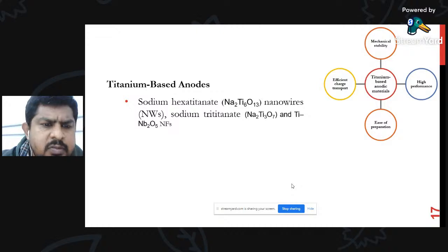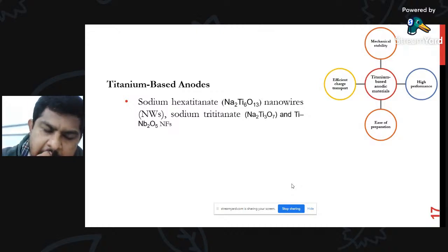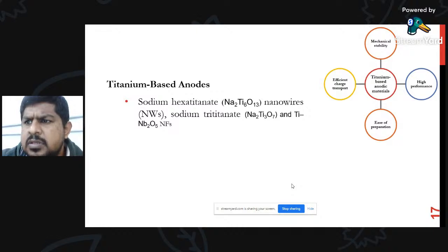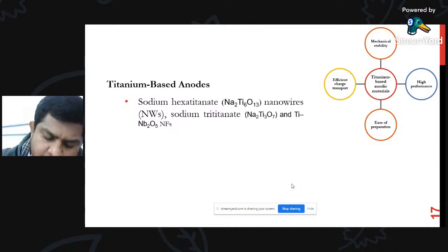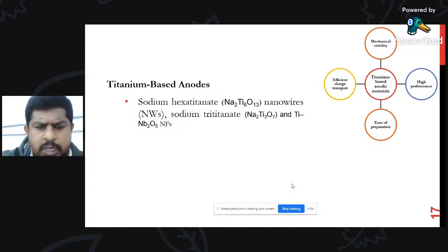So okay, there are different types of materials which are used for titanium anodes. One is sodium hexatitanate, which is used as a nanowire, and titanium with niobium pentoxide, and its nanofiber is also checked. Okay, then they have some good results actually. When they were tested with sodium hexatitanate, the interlayer spacing of the particles is a little more. Because of this, the interlayer spacing distance is more, and the sodium ion storage and diffusion is also good. So the initial testing results seem to be very good actually.